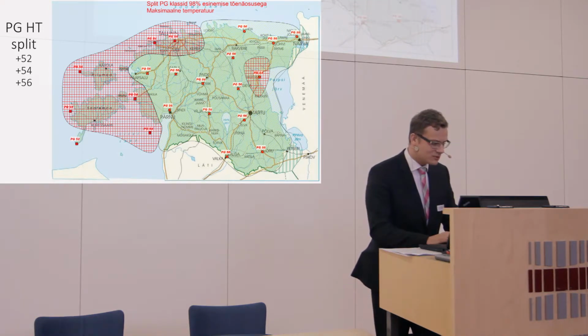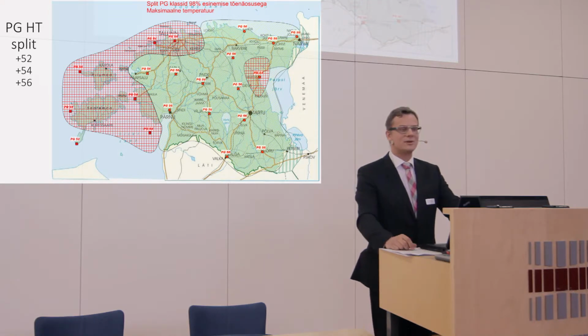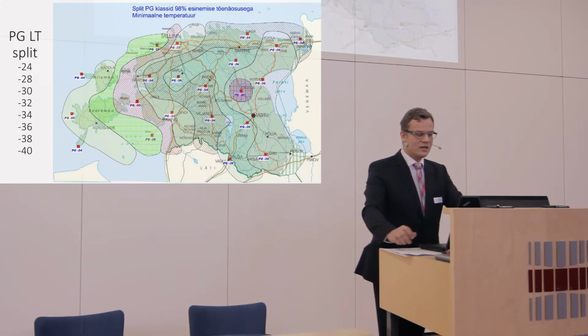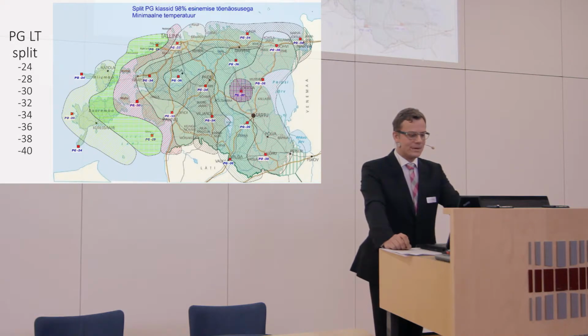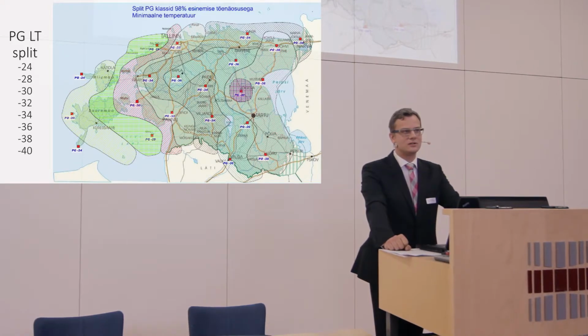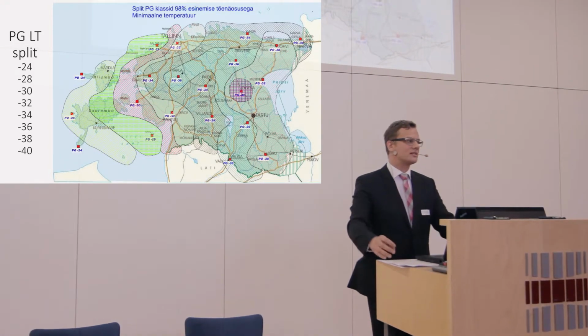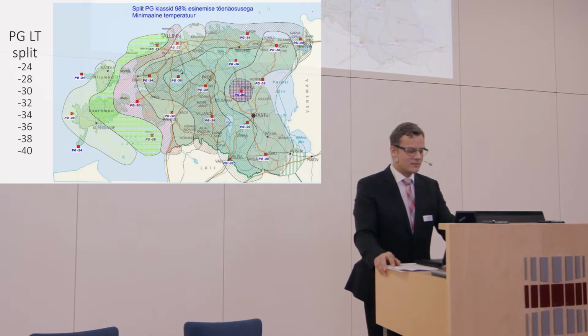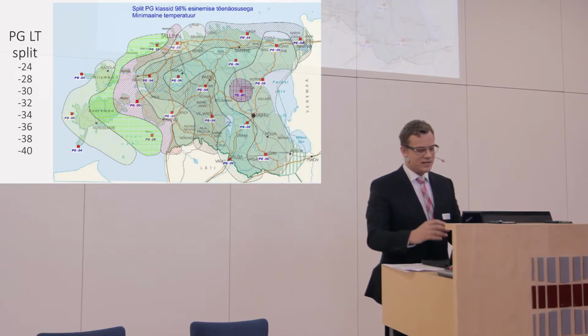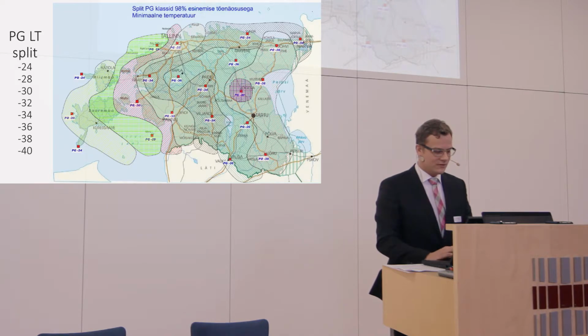Well, plus 52 only here, that's the only spot, but basically 54 and 56. When we look at the lower temperature split grade, then you have a very huge variety of different climate zones. This split grade is very useful when we look at low temperature properties, for example -40.